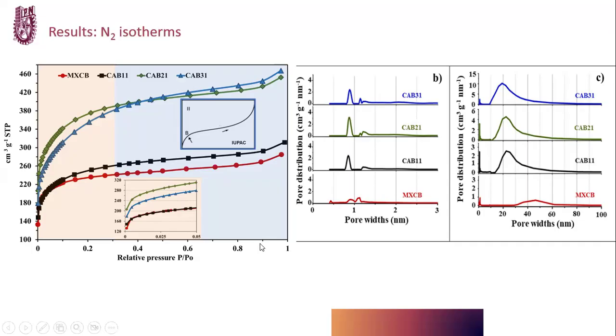From 0.9 relative pressure, the observed adsorption, this last one, is evidence of the existence of macropores. In each curve, approximately 60% of the total nitrogen uptake was attributed to the presence of micropores and narrow mesopores. In the figure at the right, we can appreciate the pore size distribution that was calculated using pyGAPS software. The intrinsic microporosity of bituminous carbon became mesoporous by the potassium hydroxide reaction.